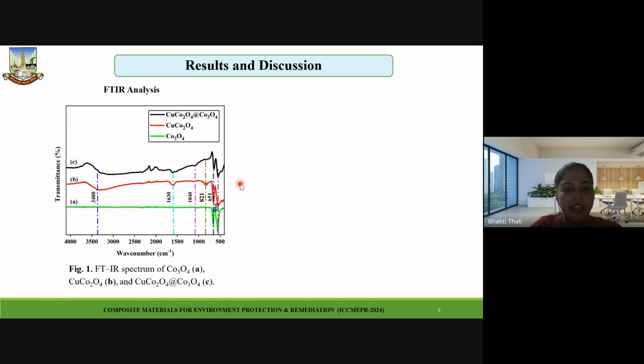So we have done the FTIR analysis. This is the FTIR spectrum of all the three materials, done to validate the presence of functional groups, and it was employed in the range of 4,000 to 400 cm inverse. As we can see, figure 1A is of cobalt oxide nanoparticles, where two peaks are seen at 555 and 651 cm inverse, which indicate cobalt oxide stretching and cobalt oxide bending vibration respectively. Figure 1B indicates the copper cobaltite FTIR spectrum, in which there are two additional peaks seen at 1630 and 3400, which indicate HOH bending vibration and OH stretching vibration.